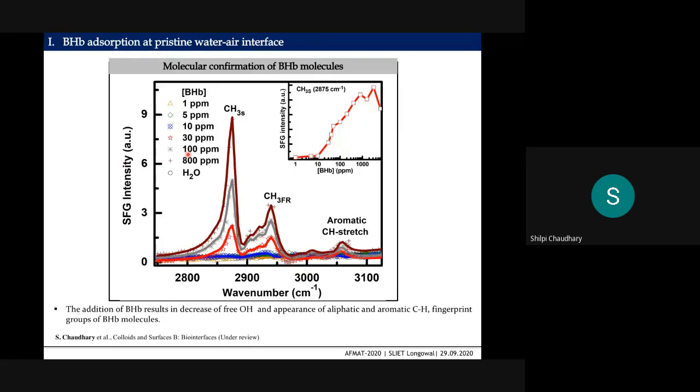In fact, at low concentration, the protein molecules at the surface have enough spatial opportunity. So what happens is that at low concentration, they will try to migrate towards the interface, and then they will have a lot of space to spread around. And since there is a presence of electronegative entities in the air, the protein molecules will start to unfold, and they will spread on the interface. But in the case of high concentration, the unfolding becomes limited by the dominant presence of protein-protein interaction. They won't go for the unfolding up to the same degree as for the low concentration. Fine.